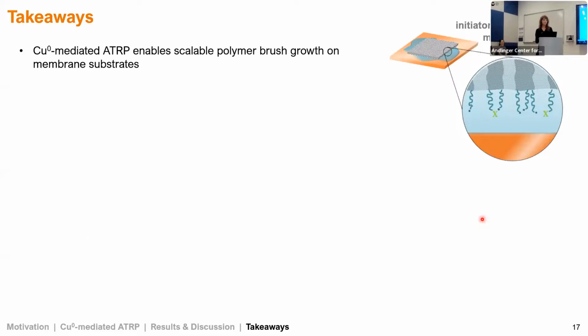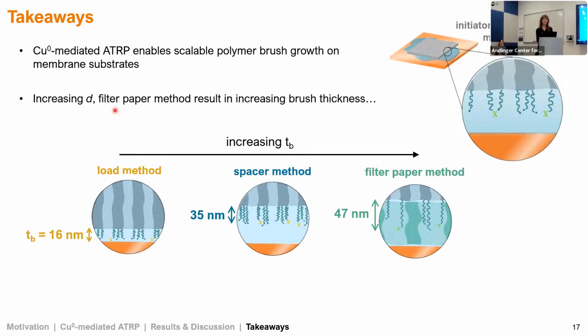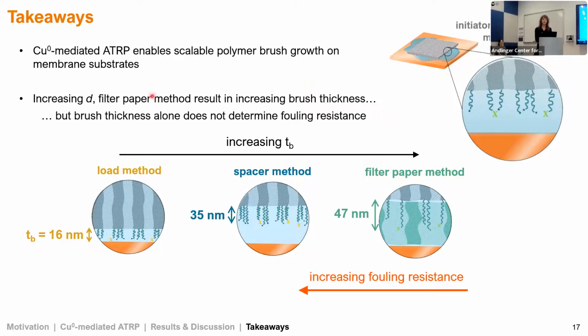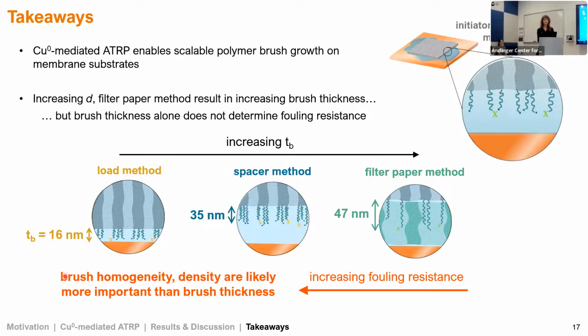Okay, so that brings me to our takeaways. First, I hope I've convinced you that copper-mediated ATRP is a viable method for scalable polymer brush growth on membrane substrates with commercial potential. Second, we looked at how increasing D and different methods, particularly the filter paper method, can accelerate brush growth and increase brush thickness. However, brush thickness alone does not determine fouling resistance. In fact, our results imply that the homogeneity and the brush density are likely even more important than the brush thickness when we're considering how to design robust anti-fouling surfaces.